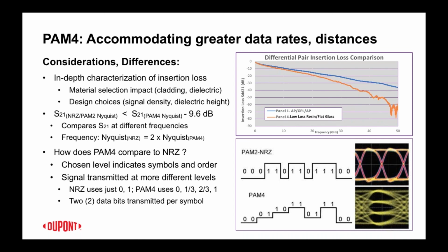So in the graph on the top right, it's showing a differential pair comparison between homogeneous materials, our Pyralux AP, and a conventional low loss resin flat glass composite. Now, comparing them at 28 gigahertz shows a pretty significant difference in insertion loss, but we're also interested in the 14 gigahertz comparison. And there, either one of them has enough of a loss benefit relative to the 28 gigahertz number, the 30 dB channel, to enable PAM4. And so the case that either one of these work is a reasonable conclusion.